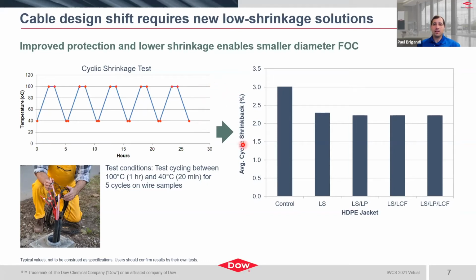And we've done some correlations which actually line up fairly close with relative performance that we've seen. And so the key takeaway, as we look at the average shrinkage following this cyclic aging, is you can see where shrinkage is about 3% for a normal control cable. We're able to lower that by almost 30% or so with the low shrinkage materials. And so what you see is obviously all these are the low shrinkage performance, relatively about the same. And so the impact of the additional functionalities do not hurt the shrinkage performance. In some cases, slightly improved, but I would say these are all about the same. And so we're able to lower the shrinkage by almost 30% in these cases.